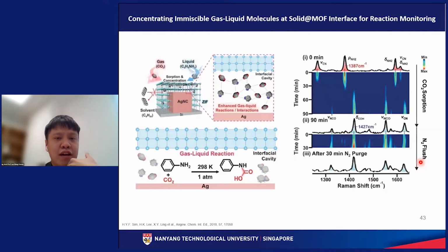The other important application is to concentrate immiscible gas and liquid molecules at the solid MOF interface for reaction monitoring. In this case, our gas reactant is carbon dioxide and the liquid reactant is aniline. We want to concentrate them right at the interface. By concentrating them, we are forcing them to interact and therefore subsequently drive their reaction. One key point about this design is that the MOF should also exclude solvent molecules from the system. Else, solvent molecules are usually present in high concentration, and if solvent molecules can access the MOF, then most of this interfacial cavity will be occupied by the solvent molecules. This is again what we do not want in our system. We just want the gas and liquid molecules to be present over here.